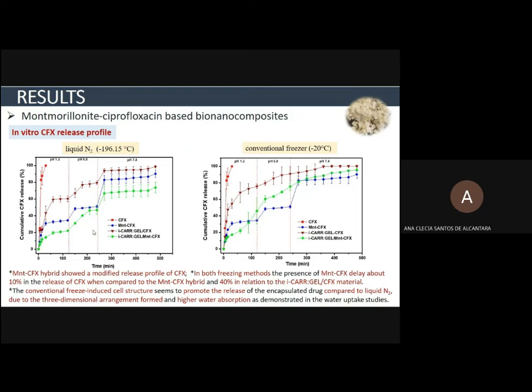But it is interesting to observe also that the intercalation compound by itself showed a modified release profile of ciprofloxacin. It's very, very interesting. But when this intercalation compound is incorporated into the biopolymer, the release is slower. Comparing the freezing methods, the cell structure induced by conventional freezing seems to promote the release of the encapsulated drug compared to liquid nitrogen, due to the three-dimensional arrangement and the higher water absorption, as demonstrated in the water uptake studies.